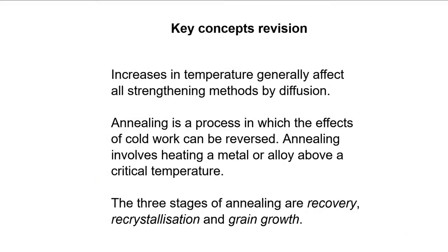So, to recap, diffusion rates increase exponentially with increases in temperature. This is aided by a correspondingly increased number of vacant sites within the crystal lattice. This has been further exemplified by what happens to the diffusion coefficient as a function of grain size. Annealing is a process in which the effects of cold work and therefore strain hardening can be reversed.